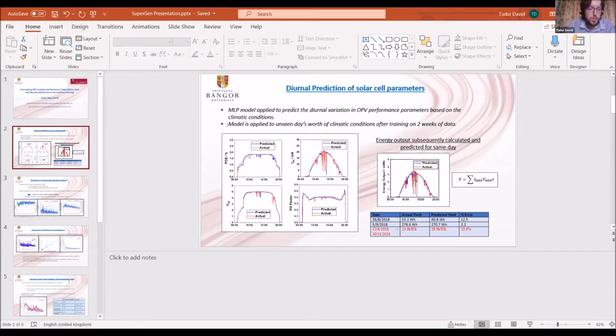Yeah. So what we've done is using machine learning to predict OPV performance and degradation. So we apply an MLP algorithm and it's trained on a period of 2 weeks of diurnal climatic conditions and corresponding OPV parameters. The algorithm is then applied to unseen days of climatic data in order to predict diurnal variation in these performance parameters. And here we can see the actual and predicted variation in the performance parameters over the course of a day.